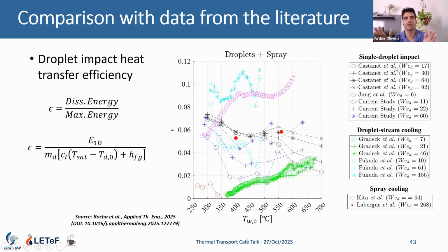When we do this for single droplet impact, droplet stream, or spray cooling, even for those very different droplet sizes, all the efficiencies fall inside the same order of magnitude. That was very nice to see, the droplets collapsing close together. And that's reasonable because the droplet mass depends on the cube of the droplet diameter.